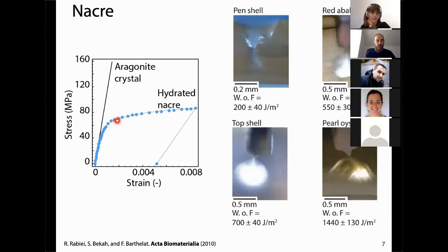Whereas when you look at hydrated nacre, you have something that looks like a yield, and then some sort of plastic zone that goes for several fractions of a percent. It is irreversible, but if you unload, you still have a sample. So it behaves as if it was ductile, although it's not really ductility in the sense of metals. What's even more interesting is that if you look at different species of nacre, you can get from very low toughness to very high toughness, and you can see this large deformation getting into the structure.